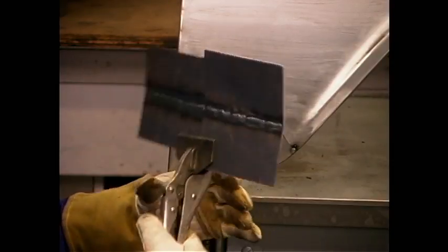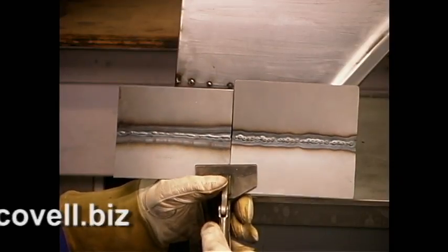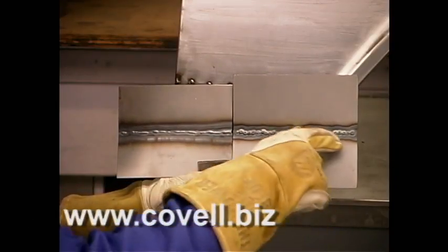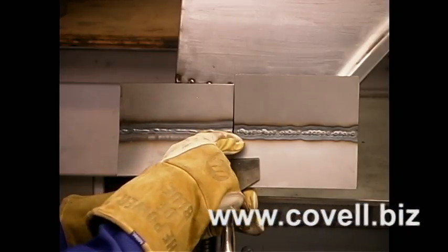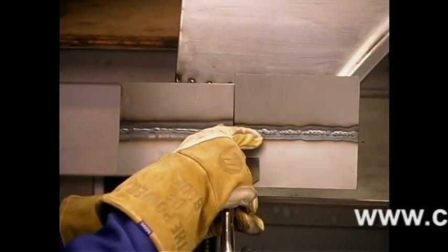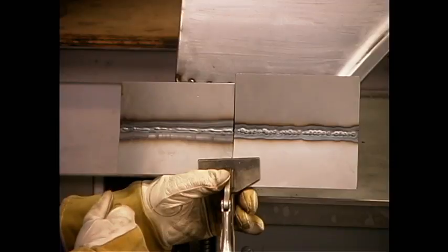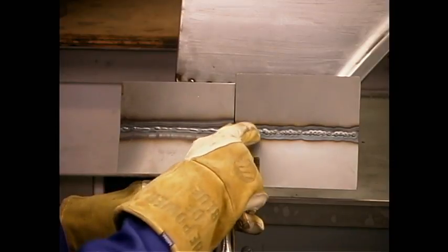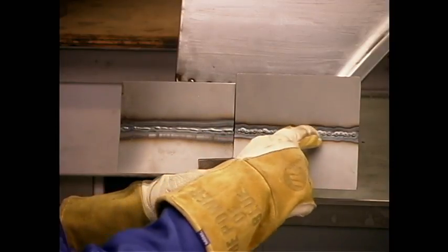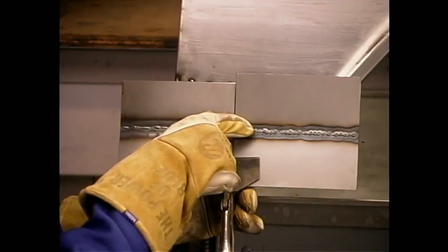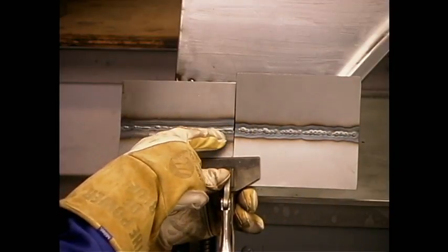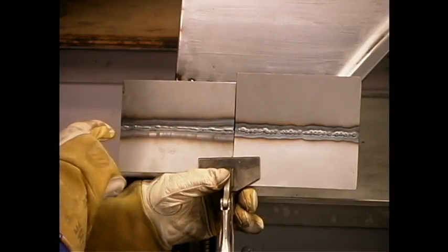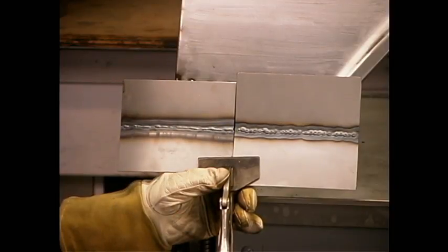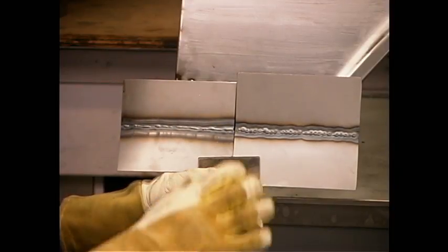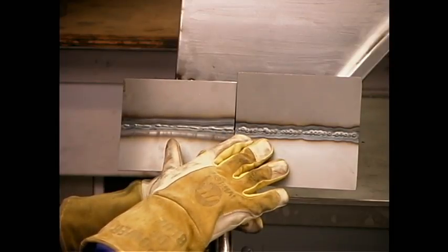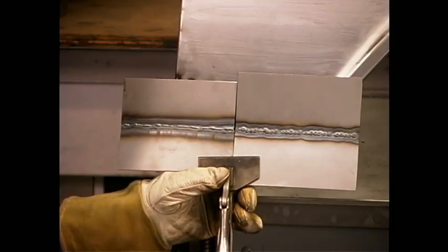Let's look at the backside now. Looking at the backside, you can see I have excellent penetration on both pieces, but what I really want you to look at is the width of the discolored area. This is what we call the heat affected zone. You can see that the heat affected zone of the weld made with a lot of spots is about half as wide as the heat affected zone of the continuously welded seam. Warping is caused by the metal shrinking in the heat affected zone. The smaller the heat affected zone, the less warping we get.